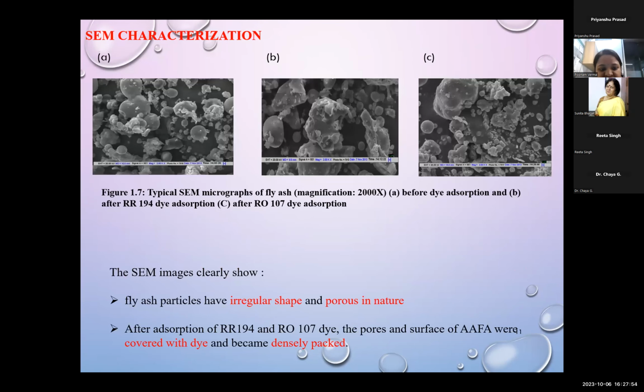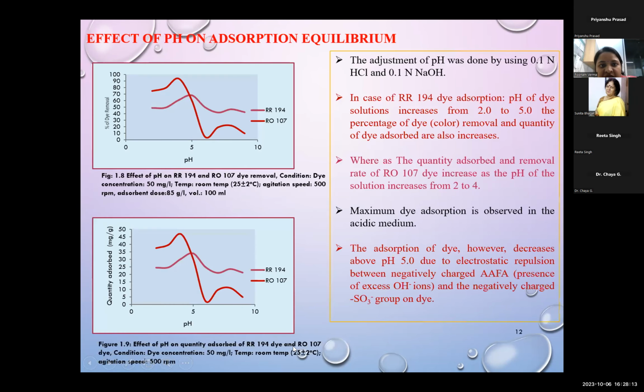SEM characterization. The SEM photograph or image clearly shows that fly ash particles are irregular in shape and porous in nature. But after the adsorption of both the dyes, the pores and surface of AAFA were completely packed and covered with the dye and became densely packed. Here are the results for the different parameters.